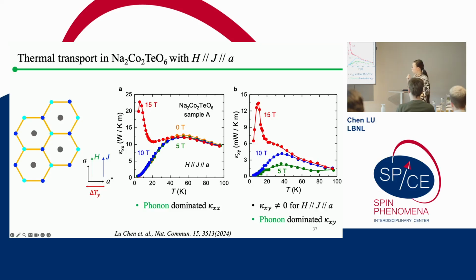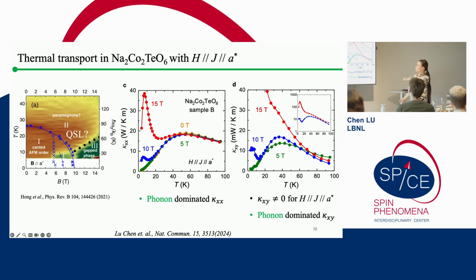Next, we try to apply the field and heat current along another high symmetry direction, which is the armchair direction. And again, we saw something very similar. What I plotted here is also thermal and thermal Hall conductivity versus temperature, which shows exactly the same thing that we got when we put the field and current along the zigzag direction. So this is a reproducible result along different high symmetry directions.